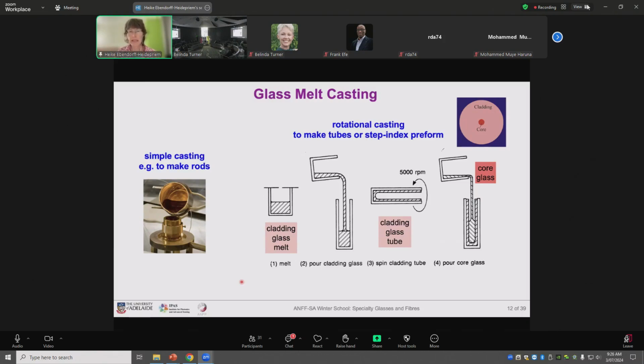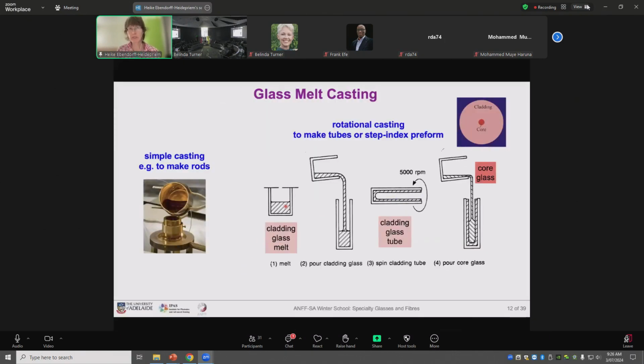So it works, we need a cladding glass and we need a core glass. We start with, we put cladding and core glass on top of each other in the furnace. Cladding glass on top so that it can be first cast into a tall, rod-shaped mold. We only fill it roughly half of the mold. Then the mold goes into a lathe, is spun in horizontal direction, and therefore we then form a tube. Then the mold is put back in the vertical direction and the core glass is cast into it. So we make the core glass preform in one go during the melting and casting.